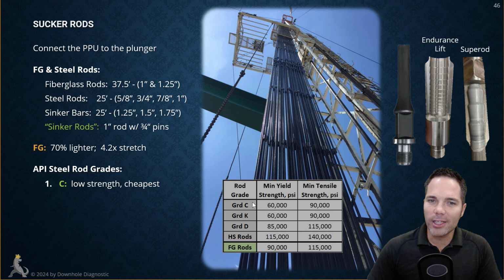The grade C rod should be able to exceed the 60,000 pounds per square inch before it starts to yield, which means it's going to plastically deform. So if you put a certain stress on a rod and it's below the yield strength and you release it, the rod is going to go back to its original position. You did not plastically deform it. If you exceed the yield strength of that rod, it will be plastically deformed, and a certain part of the rod is going to neck down and have a smaller diameter. So that is when it starts to yield. Okay, when it starts to plastically deform, the tensile strength is where it's going to pull into two pieces.